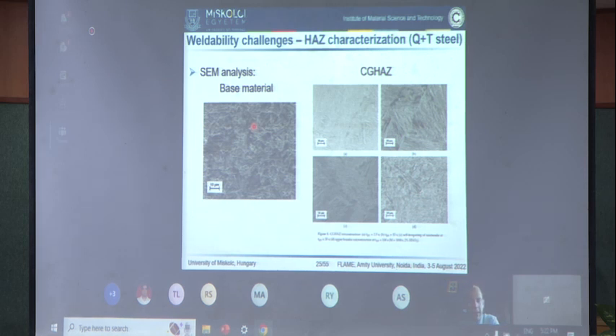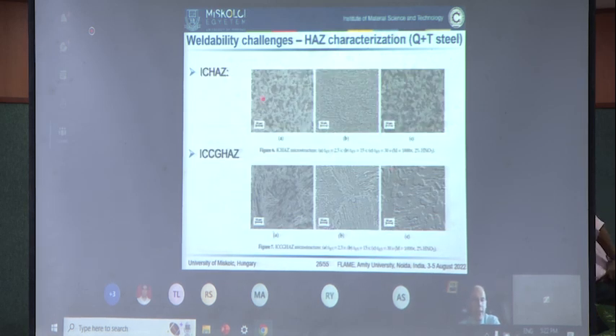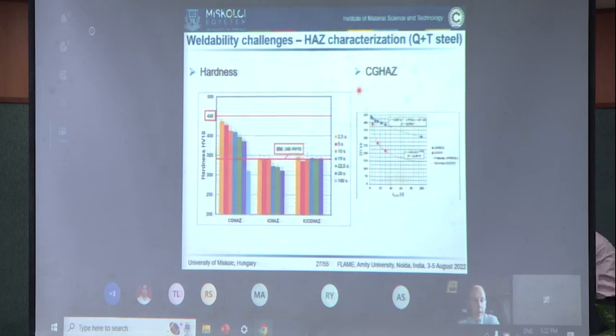So on the left-hand side, you can see the base material characteristics, and on the right-hand side, the properties of the coarse grain zone. As I mentioned, these steels generally have a martensite microstructure, but you can see that when a high heat input is used, even bainitic characteristics can be identified. In the intercritical and the intercritical coarse grain zone, you can see local brittle zones that can be observed at the original grain boundaries.